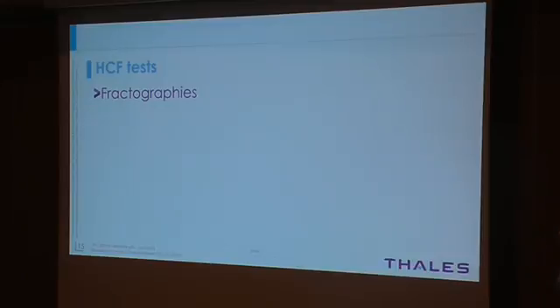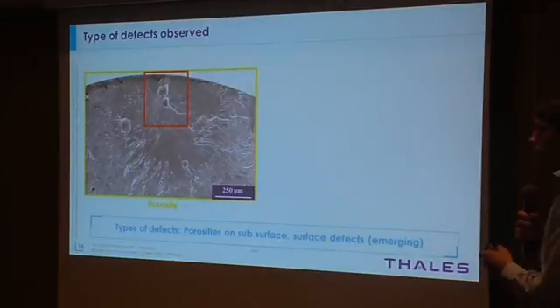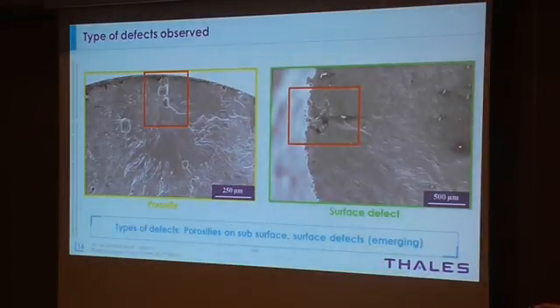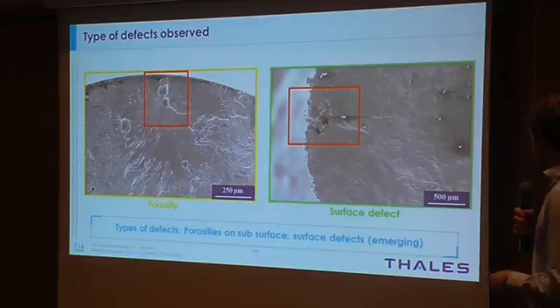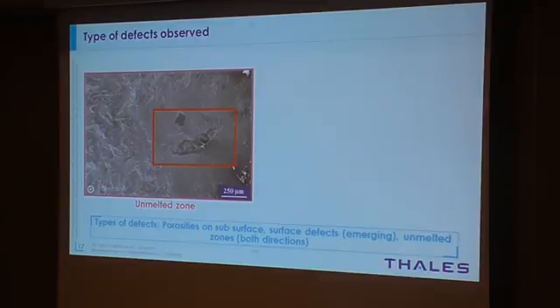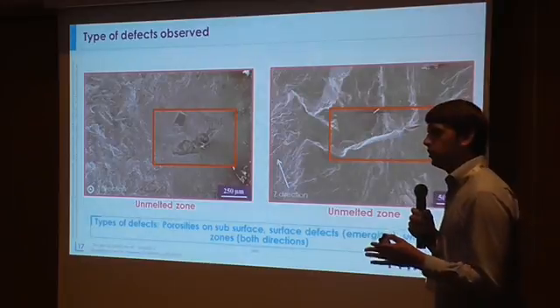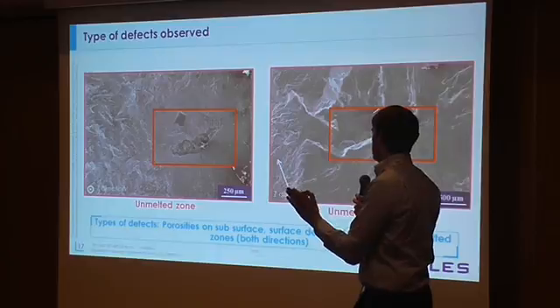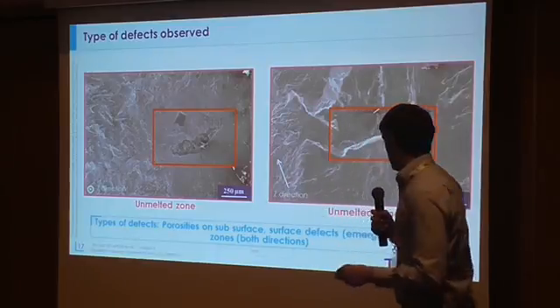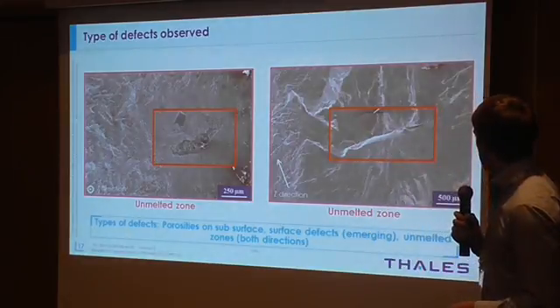Then I performed some fractographies in order to see on which type of defects the specimens failed. So we had 3 types of defects. The first one is porosity in yellow, so it's often on the subsurface of the specimen. We had also some specimens which failed from surface defects, so it's porosities which are emerging on the surface due to the high roughness. And another type of defects is the unmelted zones. So when the laser had a loss of power or little movement, we can have this type of defects. And they have a different morphology when the specimen is built in the Z direction or in the XY direction, when the layers are differently oriented.